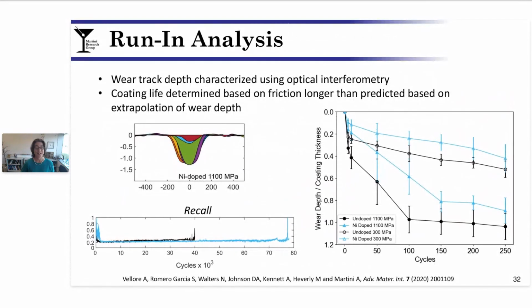All right, so let's come back first to that nickel study that I talked to you about. So you may recall that in some conditions, the nickel-doped MoS2 lasted a bit longer than the pure MoS2. To try to understand this, we analyzed the run-in phase, the first hundreds of cycles. We started by analyzing the depth of the wear track using optical interferometry. In the plot on the right, I'm showing you the depth of the wear track normalized by the coating thickness, such that 1 means that the depth of the wear track has reached the bottom of the coating.